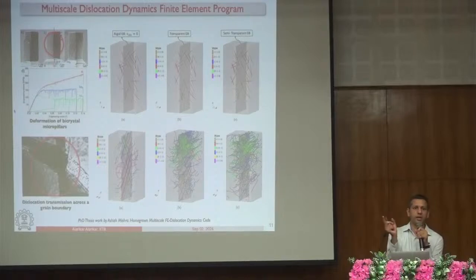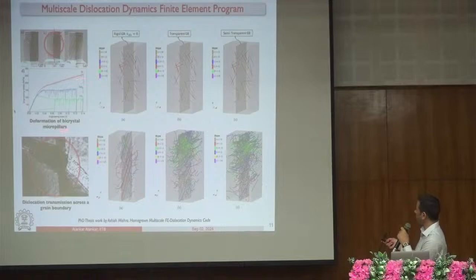So you can study multiple such bicrystals and can design your own polycrystal and even composition. If there is a grain boundary across which dislocations cannot cross, that is supposed to have higher strength. If the dislocations can cross, that bicrystal will have lowest strength and so on. And that is something that has been observed in microscopes also, and we can simulate it. So these are the simulations that we did.